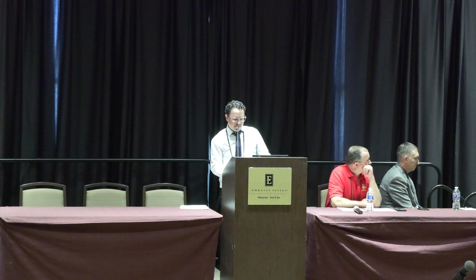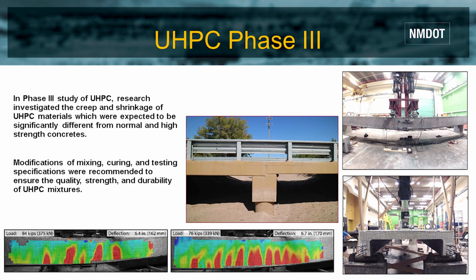During this phase, field instrumentations were initiated on bridge 9706 to monitor both short and long-term performance. I want you to note here the design you can see on the right is UHPC. It's a little bit smaller when compared to the HPC. Also in the lab, they did full-scale testing on bridge girders. This top one is the longitudinal 4-point bending, and this next picture is transverse 3-point bending.